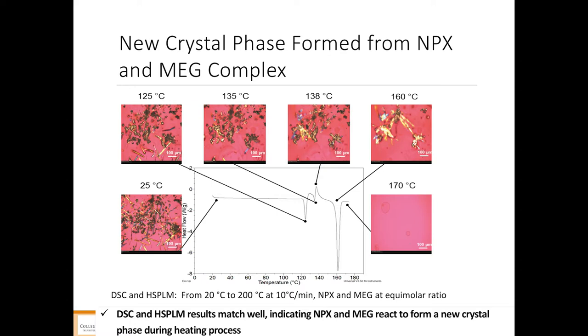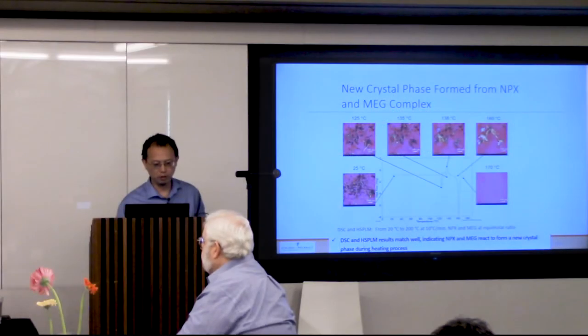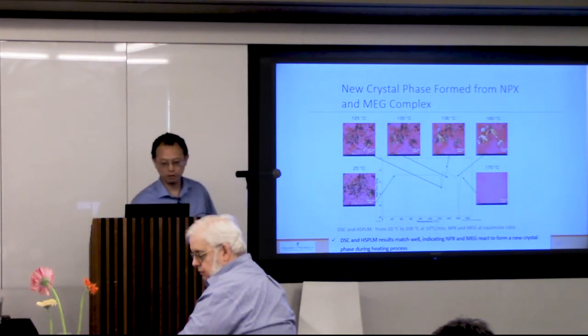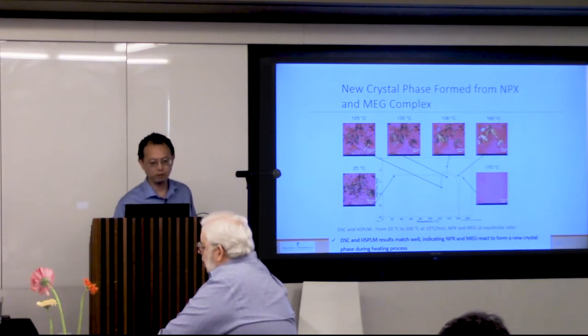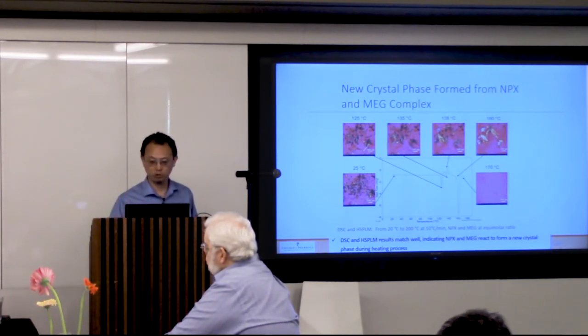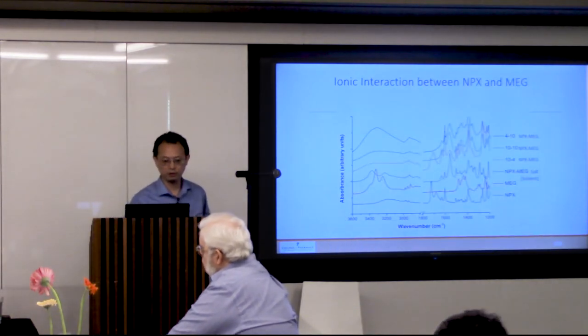Now, the fraction actually will dissolve first. And then it will form a new crystalline phase. At 135 degrees C, this is melting, recrystallizing, and then we'll melt it again. This is a new phase it formed, and we believe it's just naproxen making the salt. It has a new melting point, about 160 degrees C. And this is, again, in situ interactions.